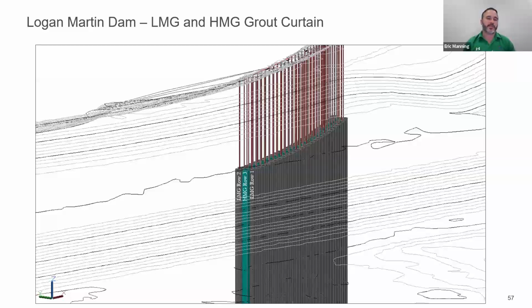We performed a proof of concept or a test section away from the embankment in an area where we had similar karst features. And what we were able to demonstrate with that proof of concept is a reduction of roughly 30% in total volume of grout. And that's considering the total volume from the low mobility grout and the high mobility grout phases of the work. So an overall 30% reduction in cementitious grout from a single line high mobility hanging grout curtain versus this three-phased multi-row low mobility grout, high mobility grout composite curtain.